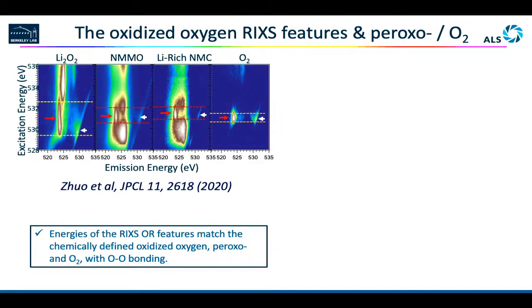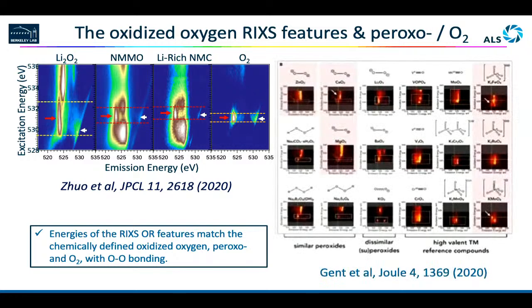And then the nature of this feature, we did a bunch of, I need to get a bit faster. So we measured a bunch of reference compounds. What we see is those are the peroxo species, all RIXS maps. I'm sorry for the busy plot here, but what you can get from this is that for all the peroxo species, we see this kind of feature, and for oxygen gas. This is oxygen gas. We see this kind of feature.